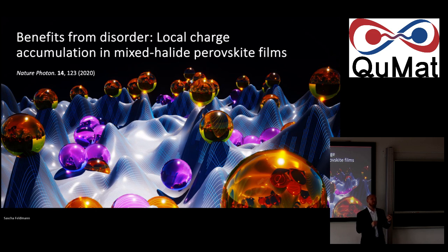We look at mixed halide, bromide-iodide mixed ones, and we see that charge carriers, depicted here as electrons and holes, really are not seeing a perfectly flat energy landscape. They see a very heterogeneous hill and valley landscape. And that means some of them might get stuck and locally accumulate.